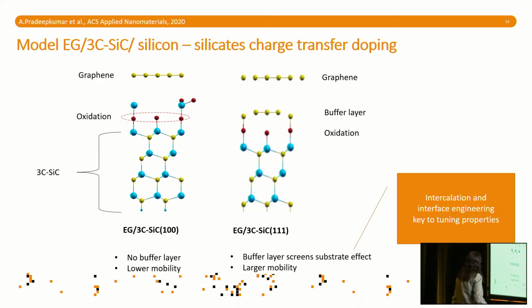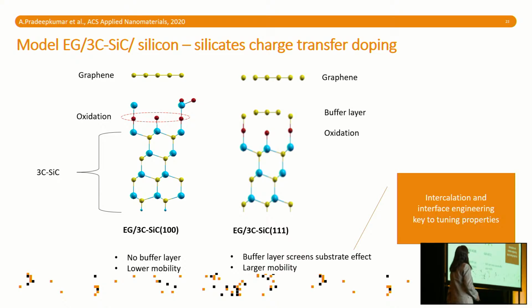And actually we understood also why we have that different distribution between working on the 111 phase versus the 100. It is because that oxidation that I talked to you about before comes back into play here, because the top of the silicon carbide is oxidized. And consequently, by graphene being exposed to that, there will be charge transfer, and it will be positive, so it will be p-type. And indeed, all of the measurements have always confirmed that at least the majority of the charge that we found in graphene is p-type. So it comes from this oxidation at the top of the silicon carbide that we create.